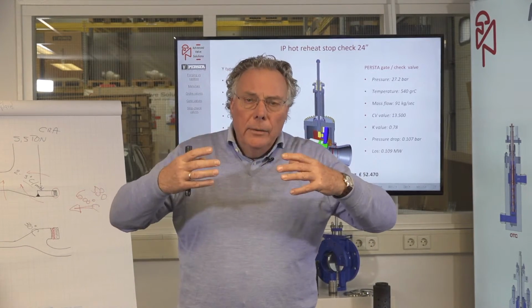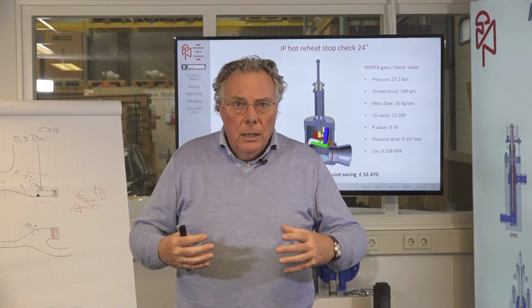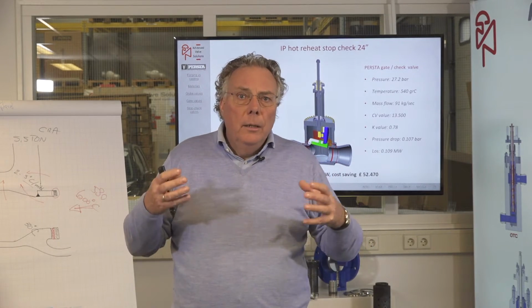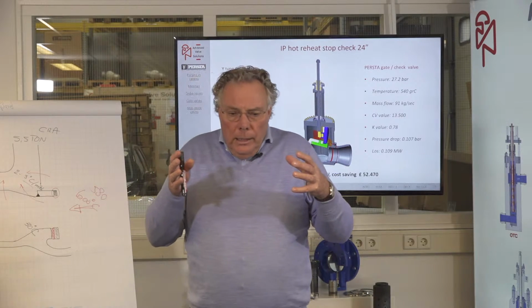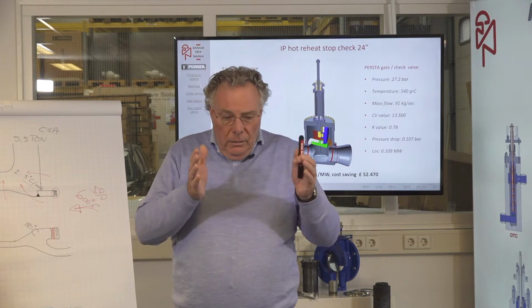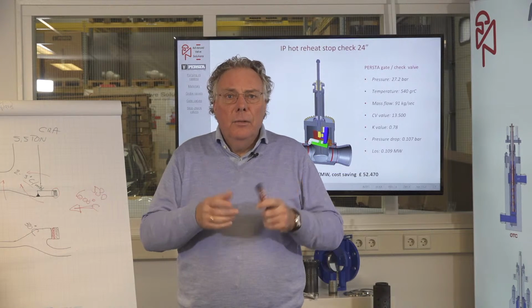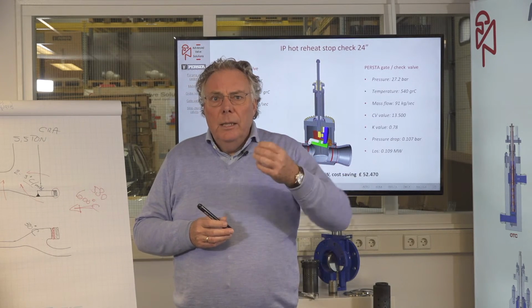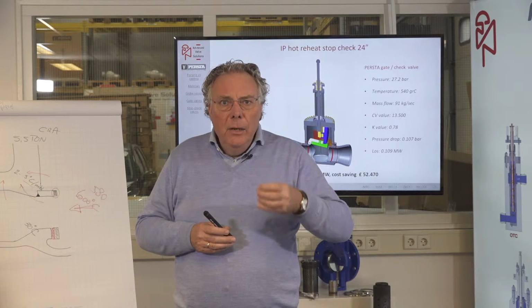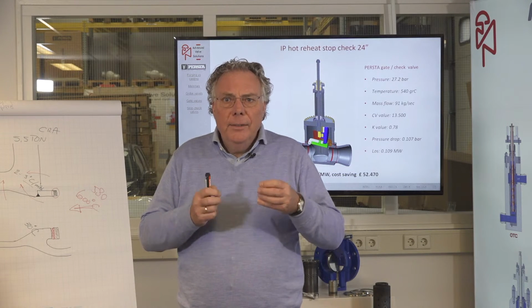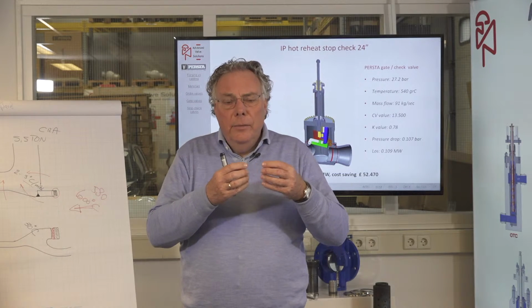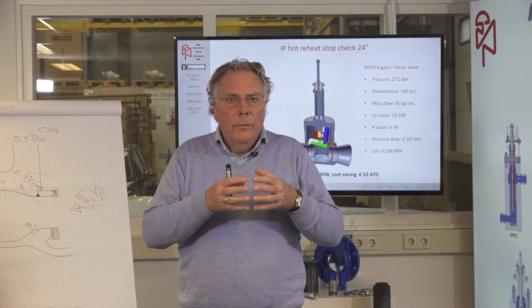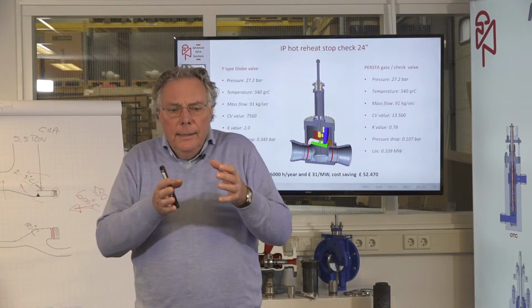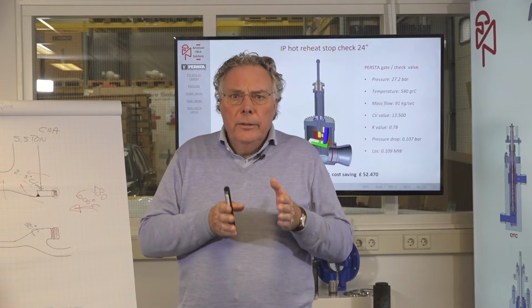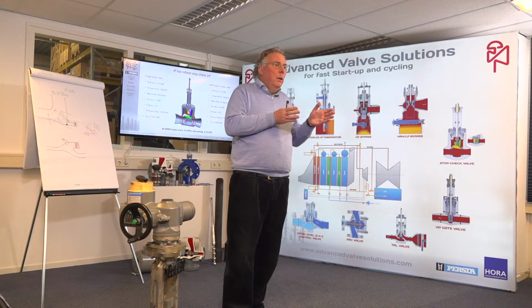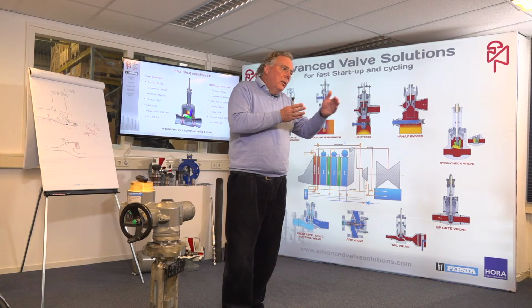And if you then go back, if I have a main steam valve based on a casting, a WC9 or a C12A casting, the wall thickness of that valve is immense, very thick. This valve is very heavy. But you can imagine that if I have casting defects in the valve body, like a thermal crack, gas inclusions or shrinkage holes, these defects influence the warming up of the valve body, because they block the equal heat transfer through it.